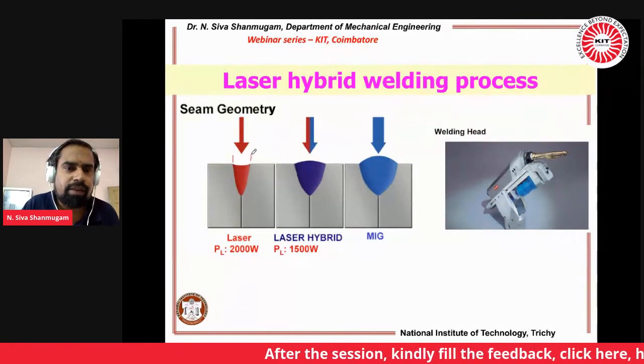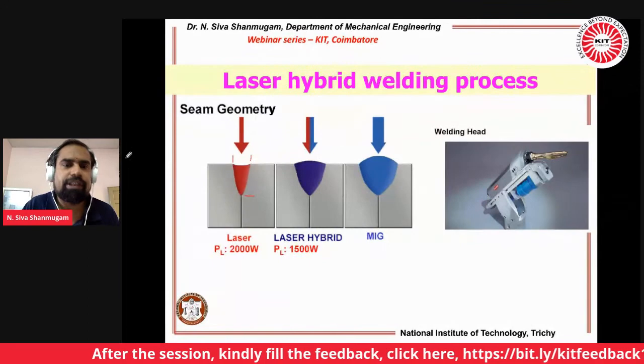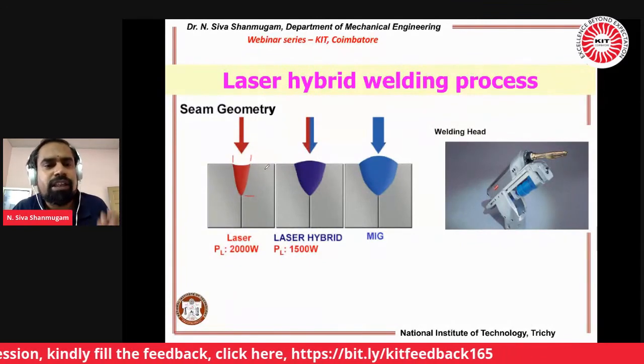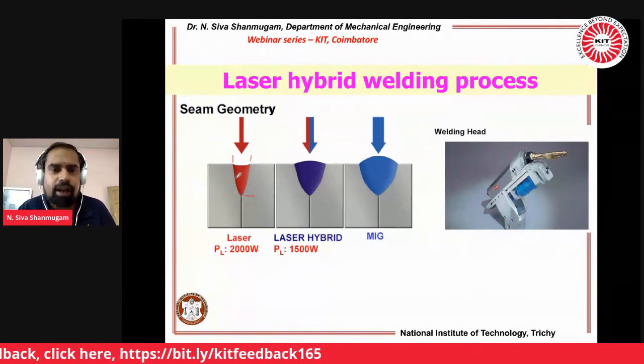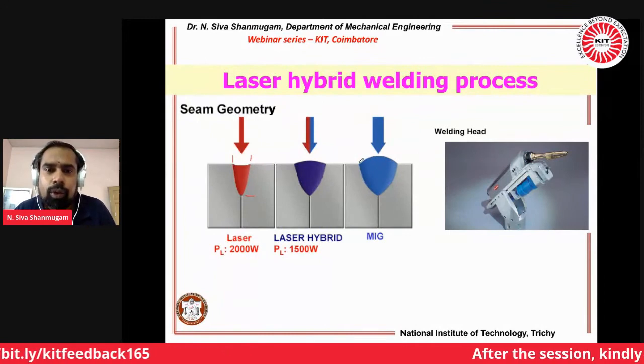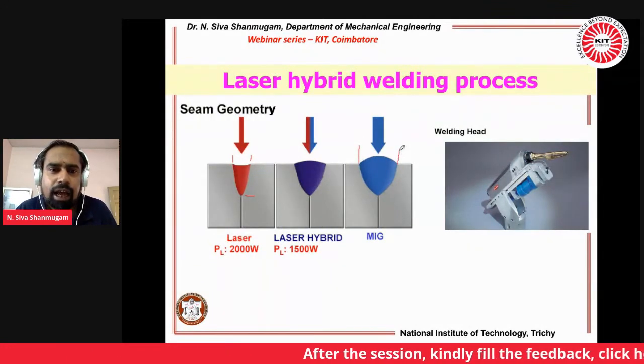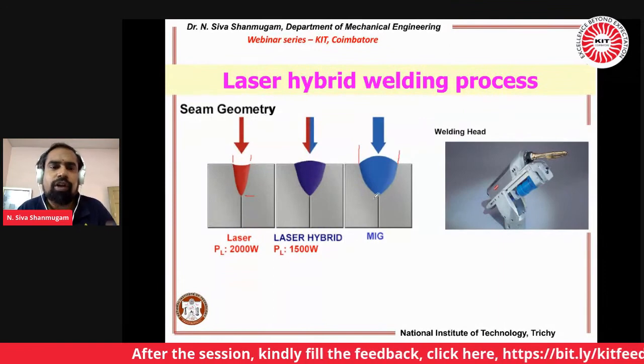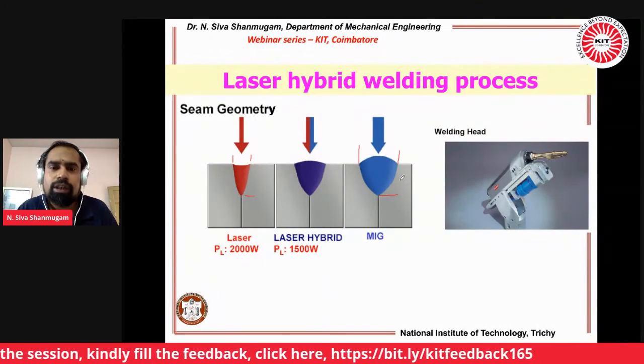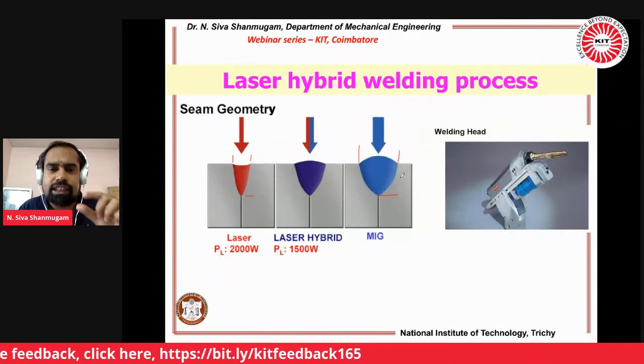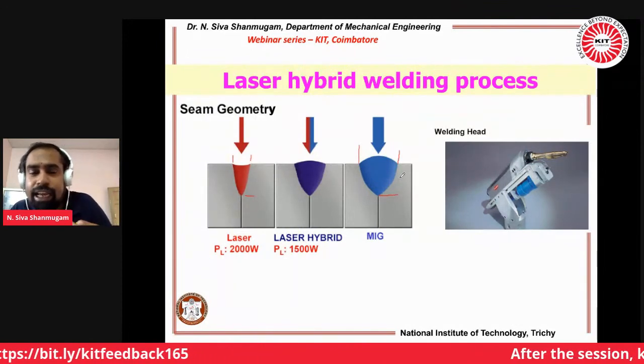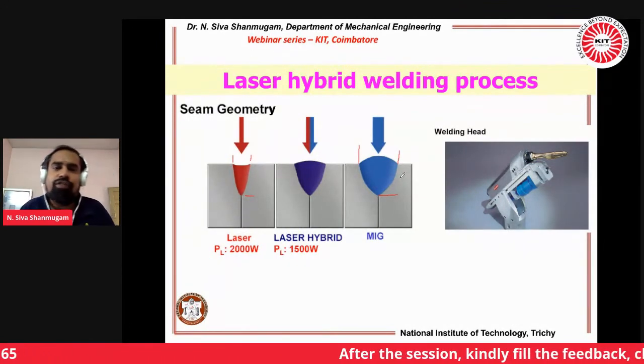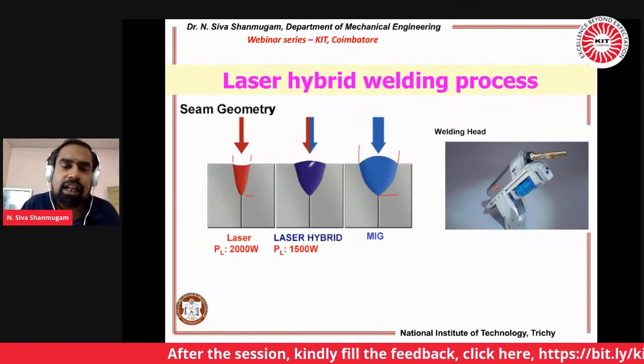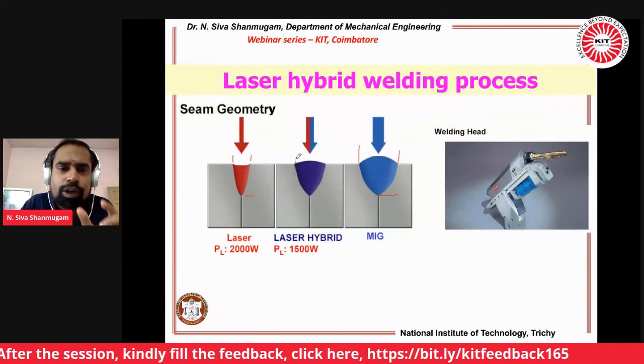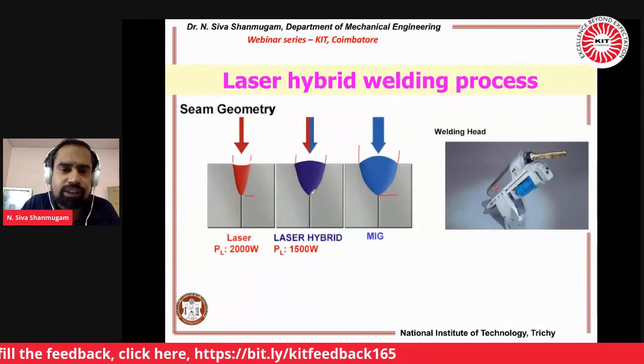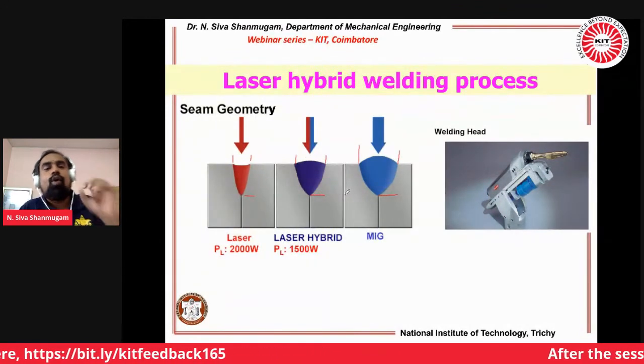So this is the bead width, and this is the depth of penetration. You see, for the laser the bead width is very, very small, but with the MIG you have a wider bead width, and the penetration, when you compare it, is very small. So the depth of penetration is small, but when you take the advantage of MIG with the laser, you can get quite a good bead width, and you can achieve the depth of penetration. Why, sir?